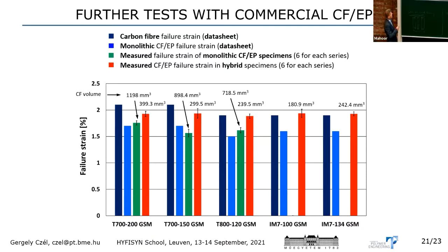And if you take a good look at the data, you can see that monolithic specimens gave quite a bit lower values than the hybrid specimens for the failure strain, but they were in line with datasheet values, so they are probably not that much corrupted.